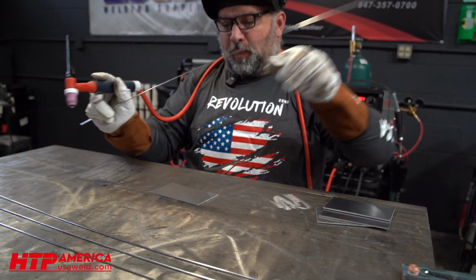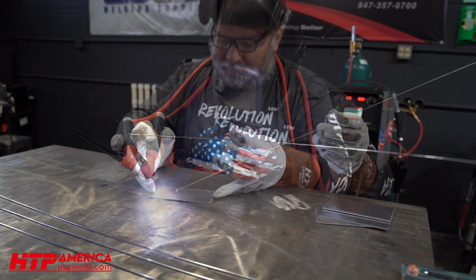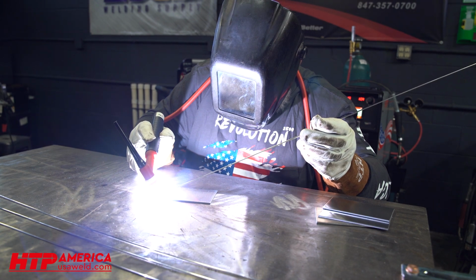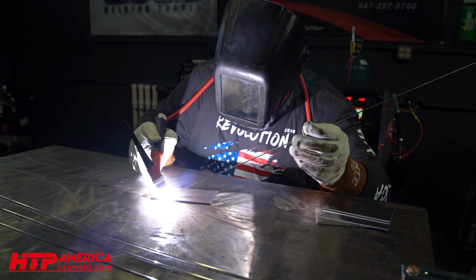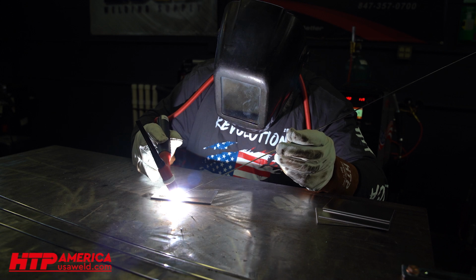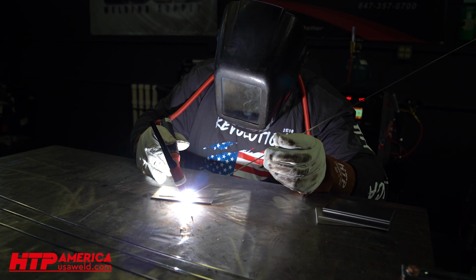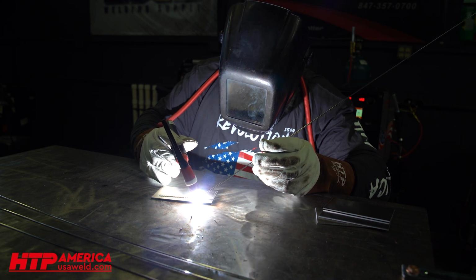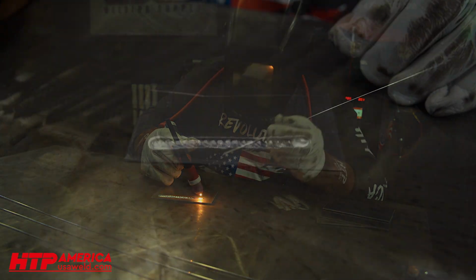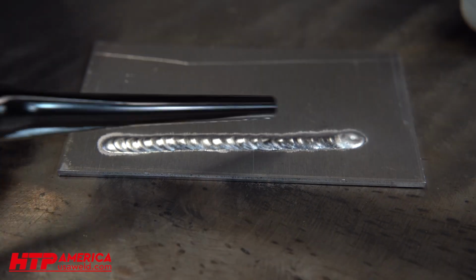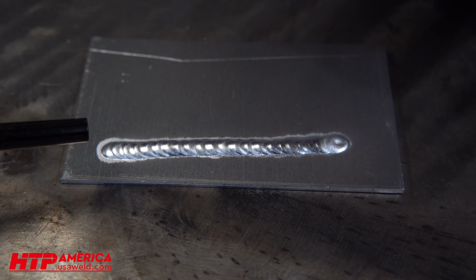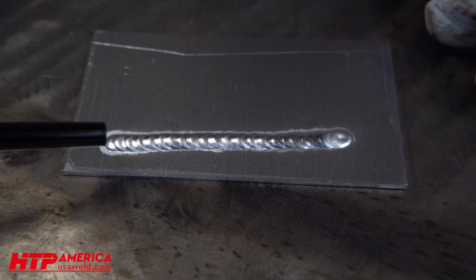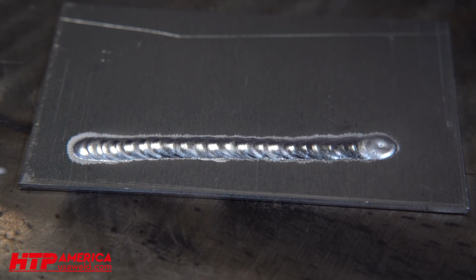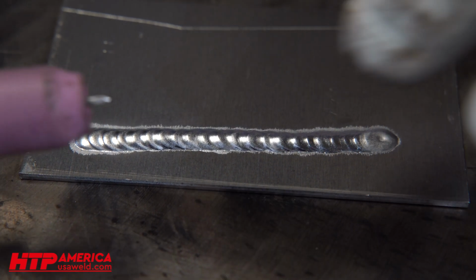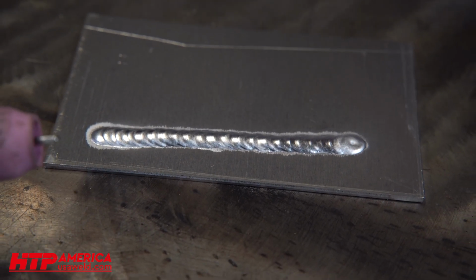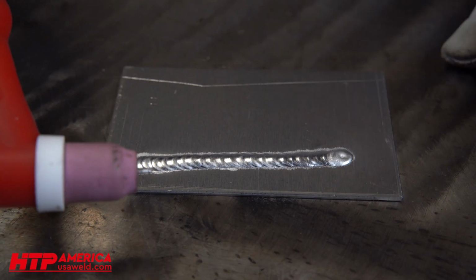The first one is 4043, 3/32 diameter. Overall clean, a little bit dull, not really shiny. No peppering, no inclusions. That's to be expected with settings like this and a clean tungsten. This is a 3/32, 2% lanthanated tungsten we're using. From the previous tests, it has a slight rounding on the end. I wouldn't call it a ball. There's still a taper left, and just the end of it is a little bit rounded over.